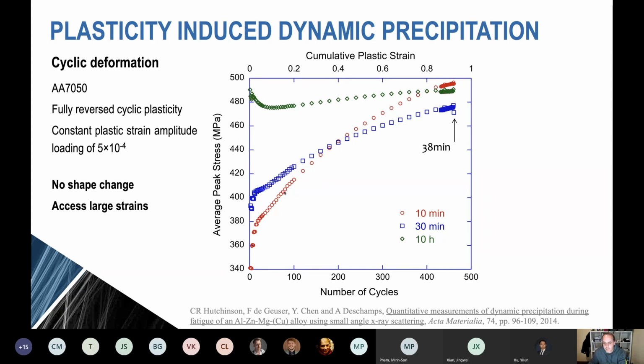But the blue and the red curves, these are underaged materials. So they're 10-minute or 30-minute aging at the normal aging temperature for these alloys. And what that means is we have precipitates present, but we also still have some solute remaining in solid solution. And what you can see here is during the cycling, we have this very pronounced cyclic hardening. And actually this cyclic hardening, we've studied and characterized by small angle X-ray scattering, and this is due to dynamic precipitation. The solute that was in solution is being precipitated out at room temperature due to this injection of vacancies from the motion of the dislocations.